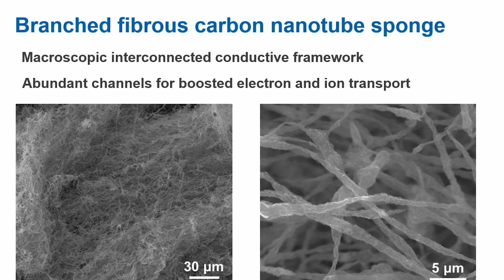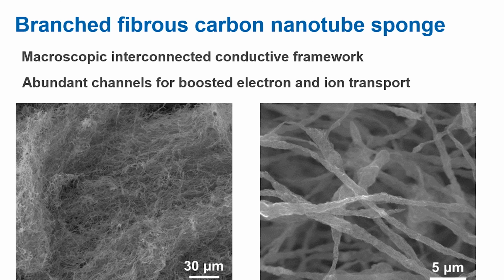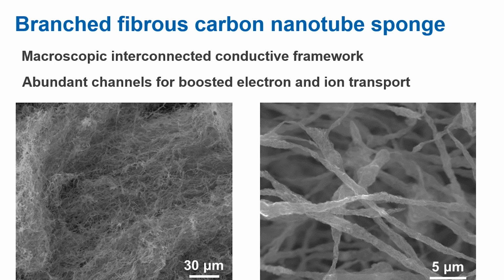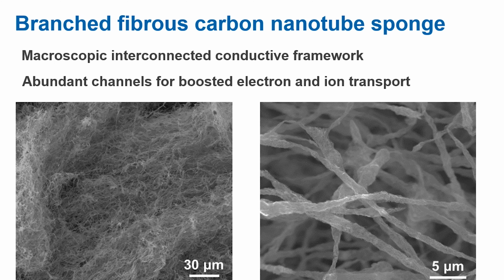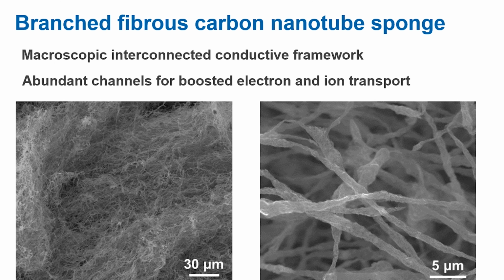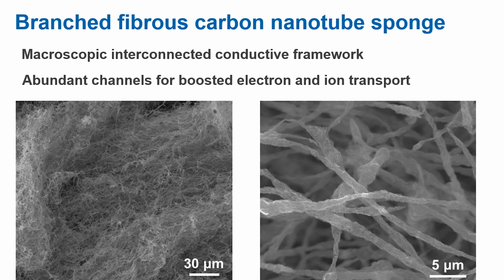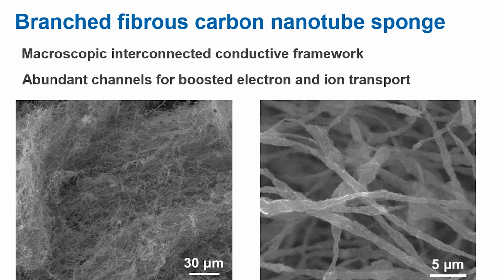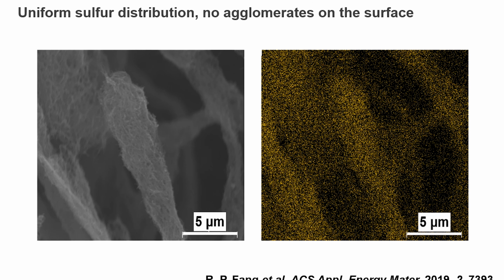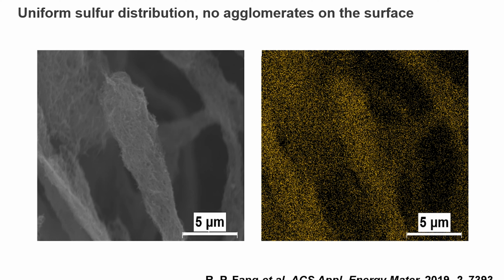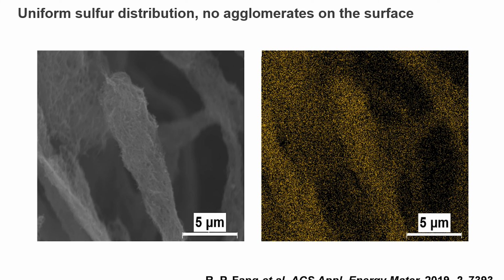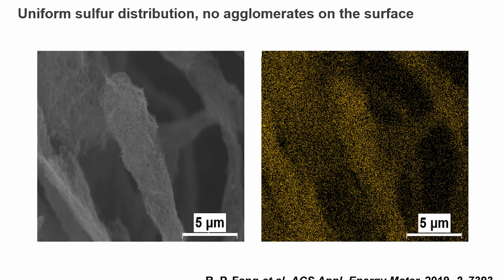From the SEM images, we can see that the sponge shows a macroscopic structure of an interconnected conductive framework, and the carbon fibers comprise carbon nanotube bundles, which can provide abundant channels for boosted electron and ion transport. Sulfur is impregnated into the freestanding sponge through a typical melt diffusion method. From the SEM image and the EDS mapping, we can see that sulfur distributes uniformly on the sponge structure and no agglomerates on the surface can be observed.